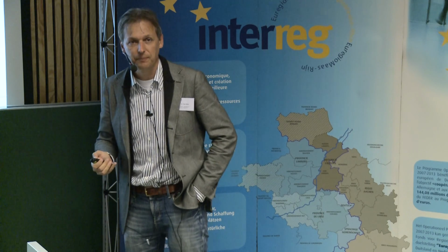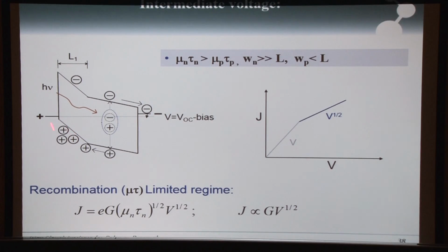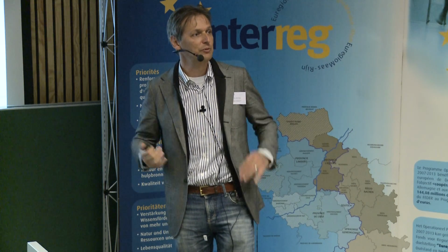So what happens now is that in order to help the slow holes out of the sample, close to this contact, the electric field will become bigger. And in order to slow down the fast electrons a bit, here the electric field will become lower. So that means that is the most important thing. In this semiconductor, the electric field is not anymore constant in the sample. So what it basically does, it adjusts itself in such a way that it will help the slow carriers, because the current as a function of distance is a constant, because otherwise carriers would just disappear.